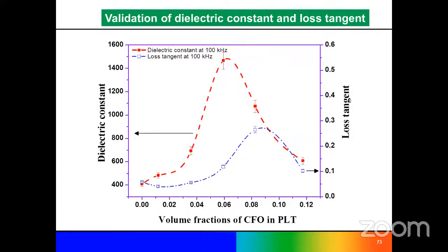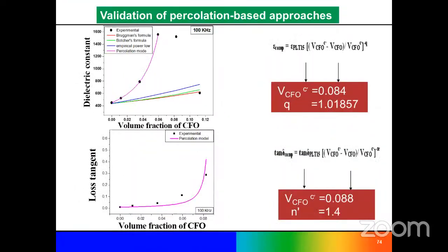If you see the dielectric property of this material, after a certain percentage of cobalt, the dielectric constant increases and then decreases with increasing cobalt iron oxide. This gives important information about the percolation of cobalt iron oxide inside the PLT15 matrix.